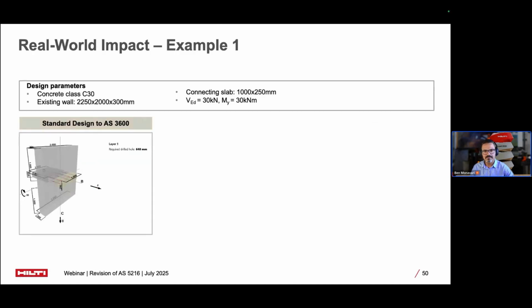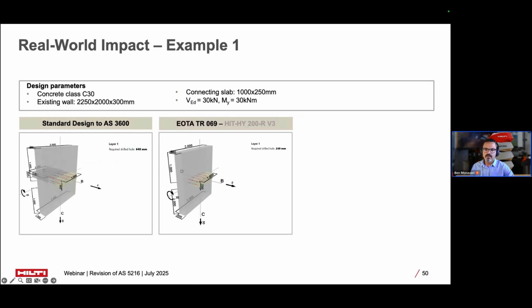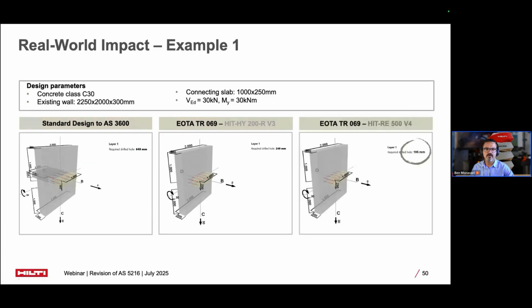Okay, so let me show you a couple of examples. Actually, there are 2 examples. The first example, we have a slab to wall connection with specific loading conditions in 30 MPa concrete. Using the standard AS3600 design method, which is equal to cast in, we need approximately 650 mm in depth, which often is impossible in typical wall constructions. And then if we go to HY200V3 as an example, reduce depth to 250 mm. And if we use RE500V4 in this example, we achieve 195 mm depth, which in this example is a 70% reduction in depth, transforming an impossible connection into a practical solution while maintaining structural integrity and safety margins.